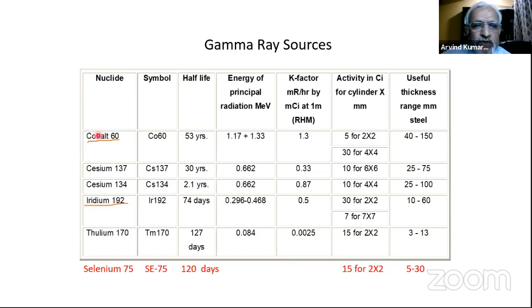Now, just to show, cobalt-60 is showing 53, but it's not 53. It's 5.3 years half-life, and iridium-192 is 74 days half-life, and selenium-75 is 120 days half-life. Half-life means, suppose today I have a 20 curie source. My 20 curie selenium, after 120 days, will become 10 curies. My 20 curie cobalt, after 5.3 years, will become 10 curies. My 20 curie iridium-192, after 74 days, will become 10 curies. That is half-life. So as we can see, the half-life of this is better than iridium, so even the sensitivity is better than iridium.